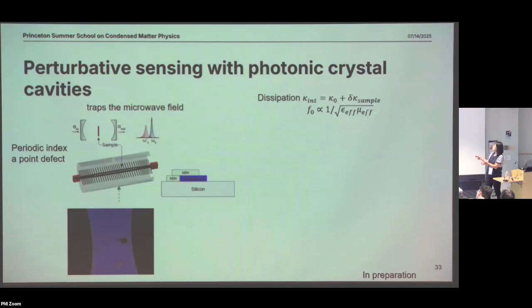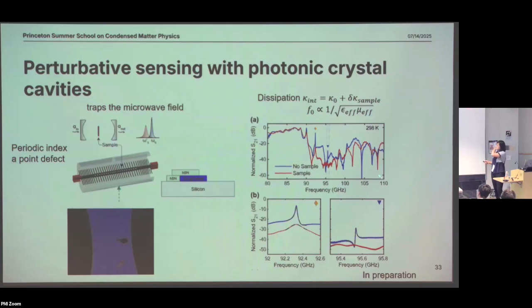So the frequency is proportional to 1 over the square root of the effective permittivity and permeability. And the sample, when put onto this photonic crystal, can effectively change the permittivity. So this is how it looks. When you have no sample, this black curve is the forbidden band region, and those very sharp resonances are by design. And then the red or orangish curve is when we put on the sample and measure the transmission between this port and that port. So that's S21.